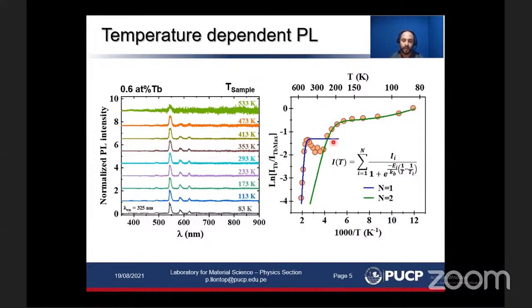And we can notice that there are two regions where a quenching occurs. There's a decrease of the intensity. So both regions were fitted with an Arrhenius-like expression, like this one, and the lower temperature region was fitted with 2 energies, and the higher temperature with 1 activation energy. We interpret these activation energies as binding energies of excitons that are bound to terbium clusters. And we believe these excitons that are bound to these terbium clusters recombine, and their recombination energy is transferred to the cluster, inducing a photon emission from the terbium ions. So as we increase the temperature, there is a thermal dissociation of these excitons that induces this quenching.